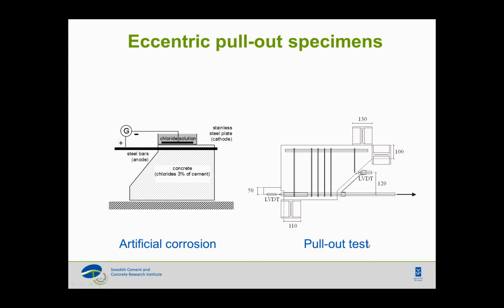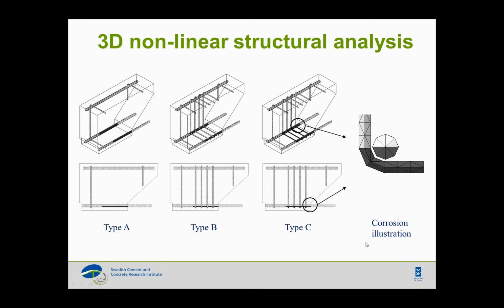So we did 3D nonlinear structural analysis at quite a detailed level. We had, of course, the concrete modeled with solid elements, but all the reinforcement in these specimens was also included with solid elements. We also had the interface elements between the reinforcement and concrete, and in the shaded areas, that's where we have the corrosion model imposed in the model. So now in the figure to the right, we look at 1 stirrup and 1 main reinforcement, and the shaded area is where the reinforcement was subjected to corrosion in the lab, and that's exactly how we try to implement that in the simulations.